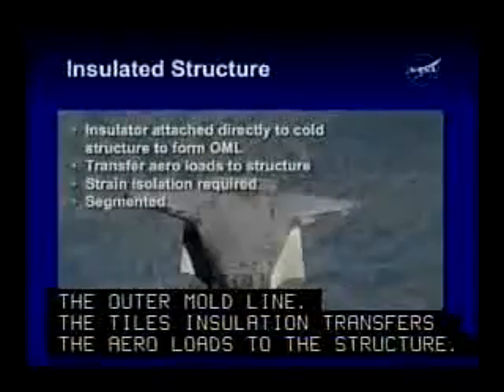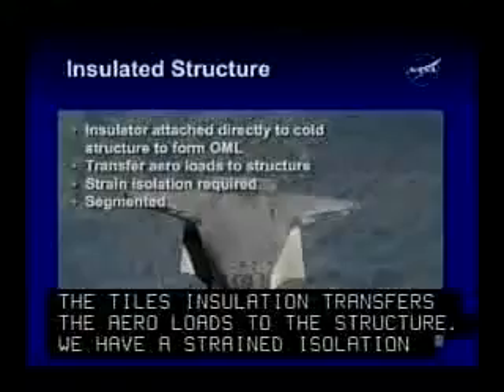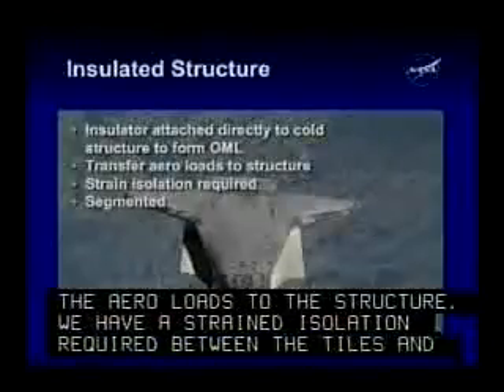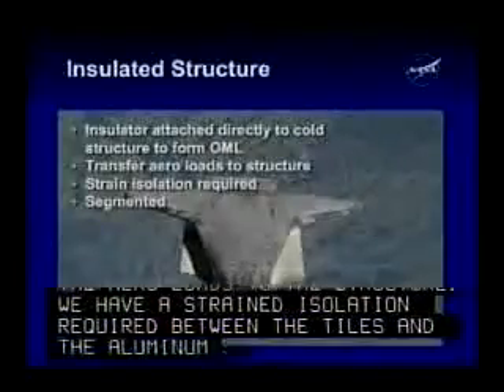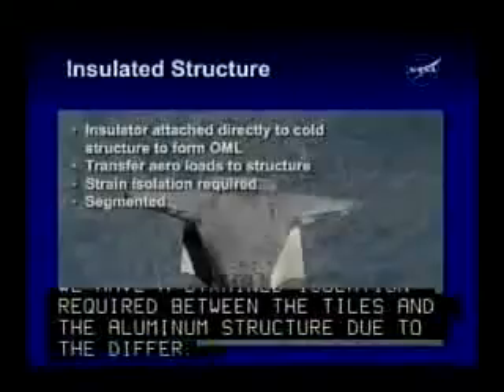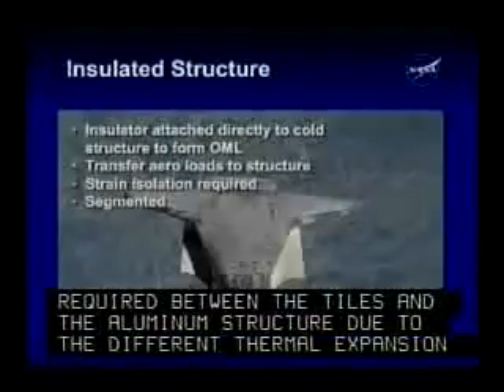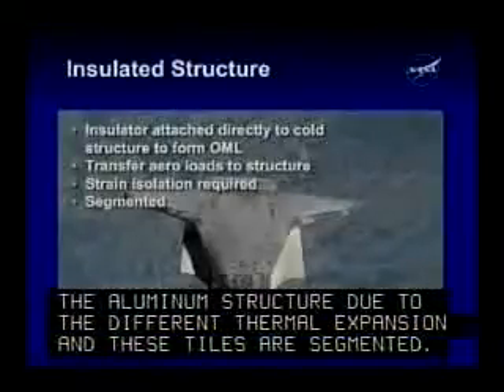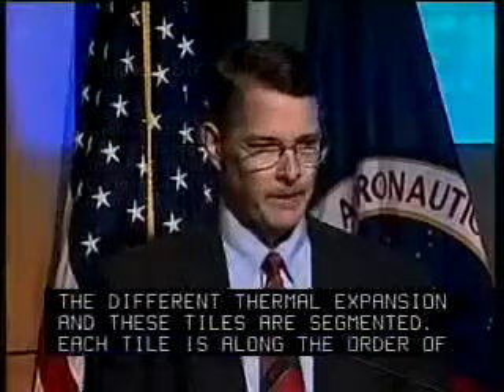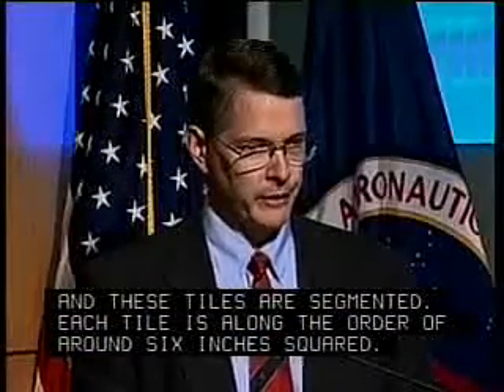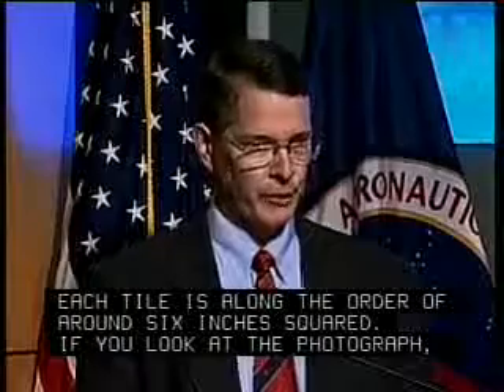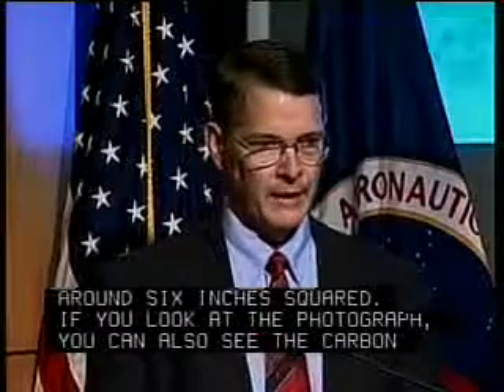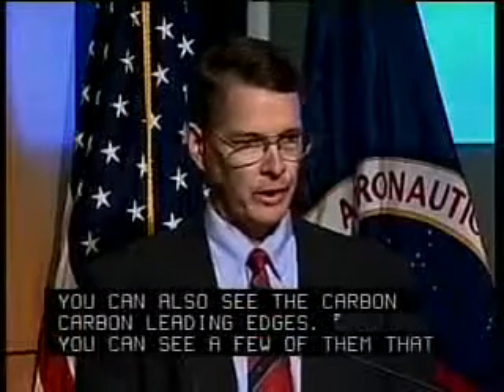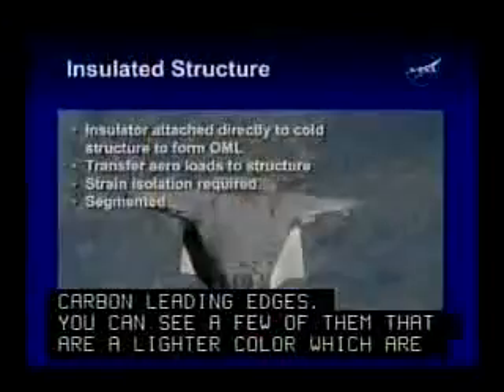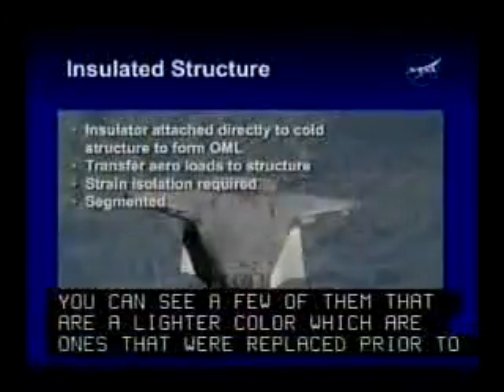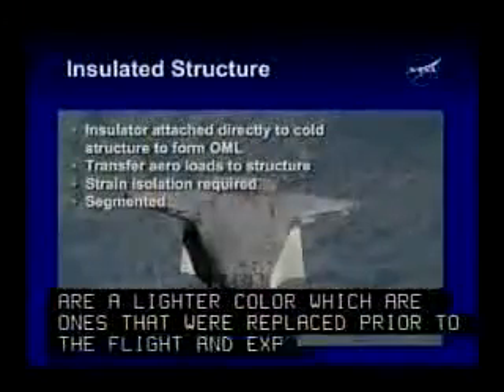We have a strain isolation which is required between the tiles and the aluminum structure due to the different thermal expansion. And these tiles are segmented. Each tile is on the order of around 6 inches square. If you look at the photograph, you can also see the carbon-carbon leading edges. You can see a few of them that are a little lighter color, which are ones that were replaced prior to the flight and have not experienced a reentry yet. Next chart, please.